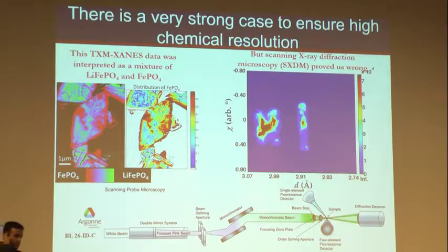And we see 3. We not only see 3, we actually see a continuity of intensity in 2 theta between the one on the left and the next one. And so what this told us is that these particles, which were exactly the same as the ones that I'm showing you on the left, we interpreted them as mixtures of lithium iron phosphate and iron phosphate, but in reality, they had a solid solution. They had an intermediate composition that has also iron 2 and iron 3 by virtue of being intermediate. And what we think is happening is that iron 2 and iron 3 in those structures are quite clustered, so that they almost look like isolated iron 2 and isolated iron 3.